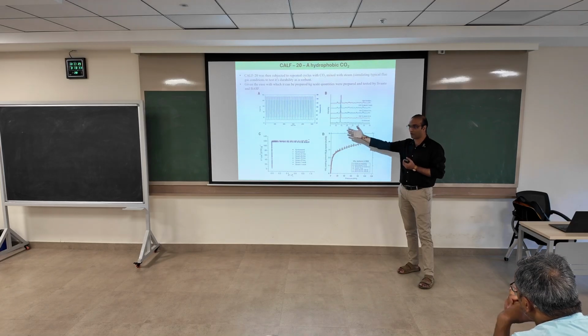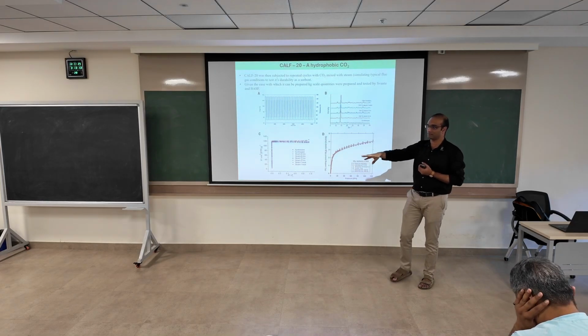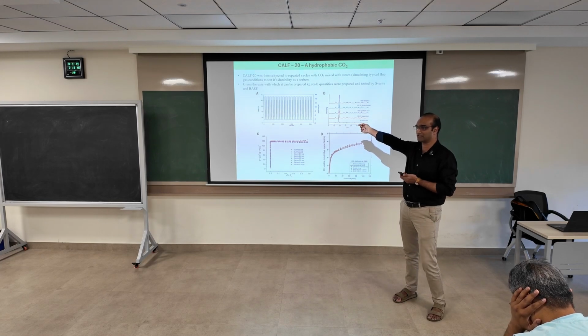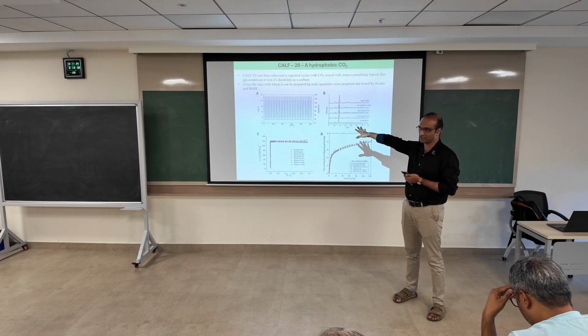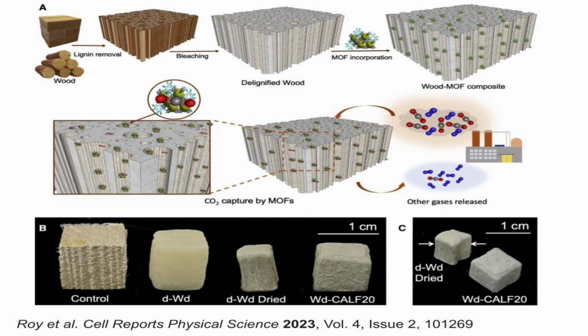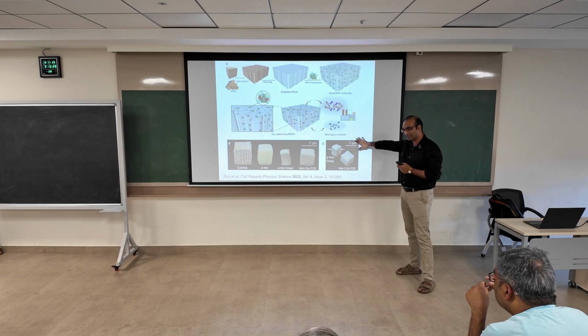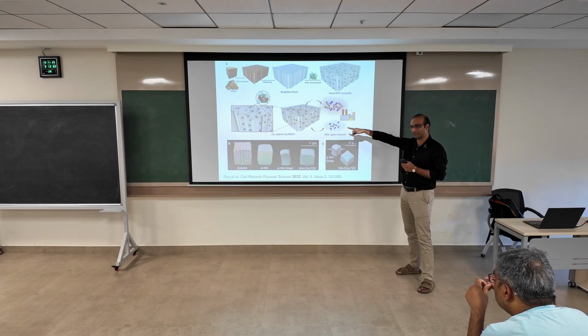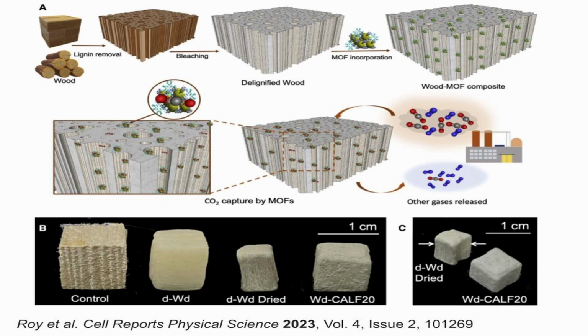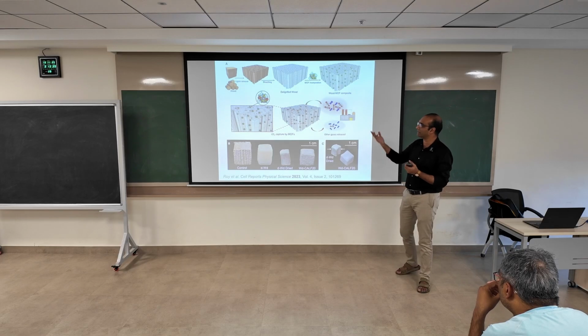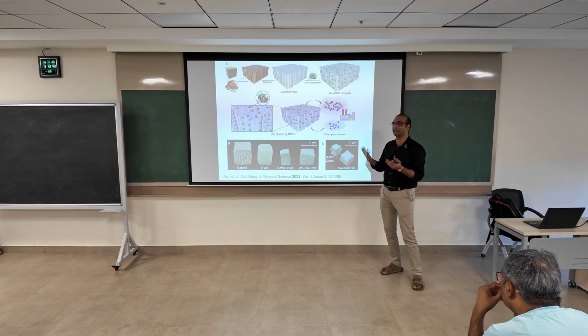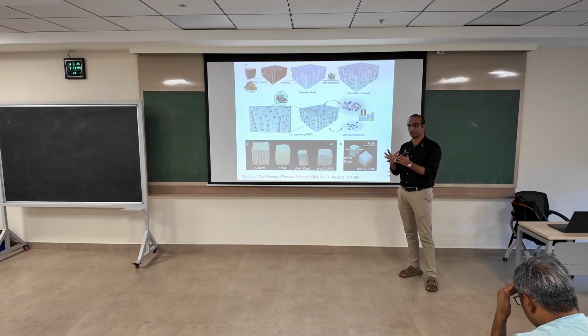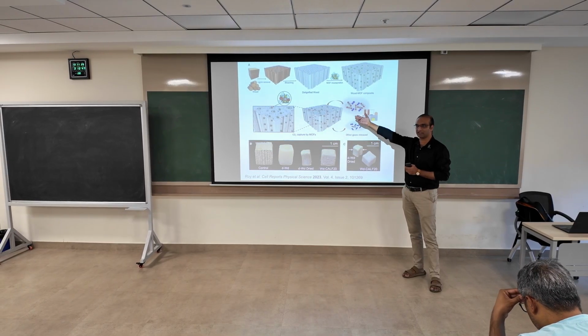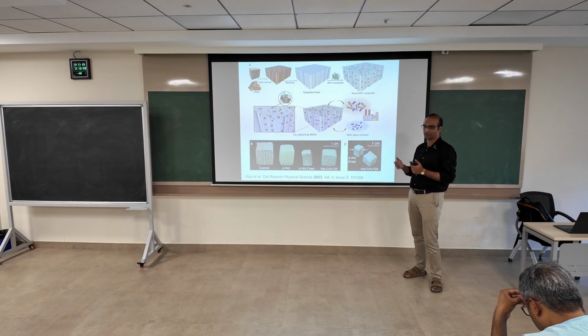And all the materials, like the zinc salt that they use for this and the oxalic acid, everything is very cheap. It's not very cost intensive. So yeah, then people have tried another paper where they had some problems publishing this paper because the company that published the other paper, the Science paper, had already patented the molecule, the CALF20, right? But they still got permission from them and they did this. It's another application where you put it in lignin and you can even increase the surface area even more. Instead of having all the powders together, you can spread it out even more on this lignin and then show its application for carbon capture, CO2 capture.